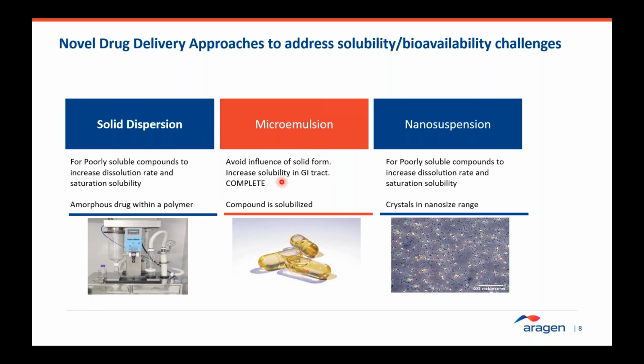The second approach is a lipid-based microemulsion formulation, suitable for highly lipophilic compounds, with a very high organic content in terms of oils, surfactants, and solvents, which are not quite safe compared to the hydrophilic polymers we use in solid dispersion. And a nanosuspension, where the drug is still in a crystalline state with particle size reduced to the nano size, increasing the surface area several-fold to improve dissolution. It doesn't improve the solubility as such, but it could be a good approach for certain kinds of molecules.